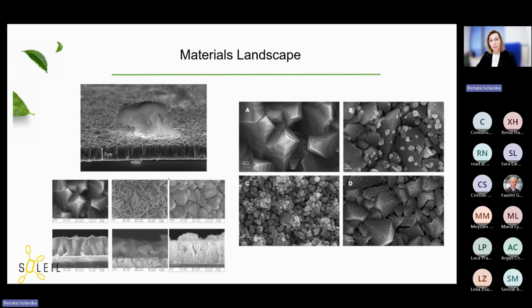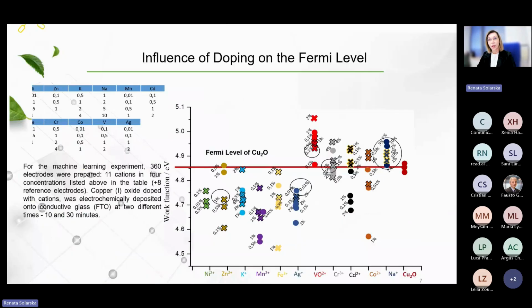and you see on the left side the morphology of the copper 1 oxide itself. And on the right side, this is the morphology of the copper 1 oxide after the photoelectrochemical run. Depending on the cutoff filter, we can produce different morphologies of the copper and metallic copper nanoparticles. So the photocorrosion depends on the photocatalysis run and on the equipment.